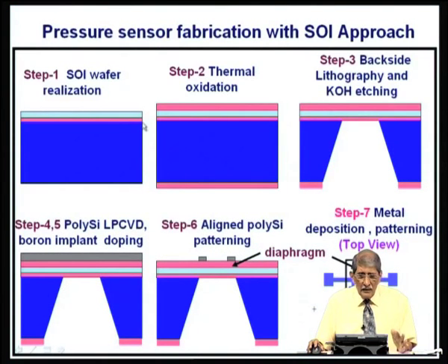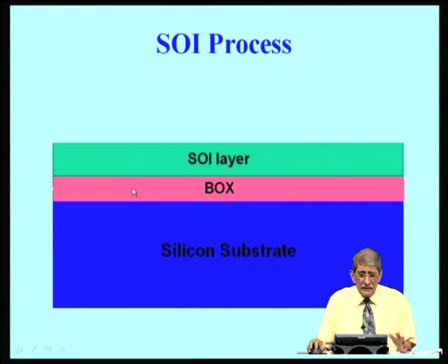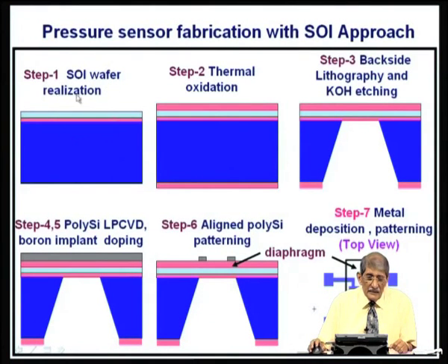Let us go through further. How is the pressure sensor made on this? Starting with the SOI wafer that is realized, silicon, buried oxide in red color, that is the SOI layer. Grow oxide on the top of that, because you are going to put resistors on oxide. So, on this SOI layer, grow oxide and then do lithography from the back side, open this oxide, and subject it to etching. So, etch it all the way down, this oxide thickness will be just about 0.5 microns. So, this membrane is 10 micron, 15 micron depending upon what you want for the membrane.